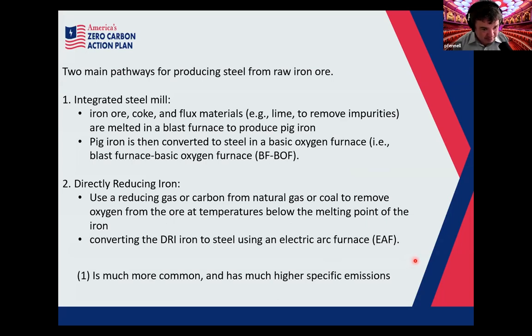There's demonstrations going on, but you have to worry about how much hydrogen you actually need to pull off directly reduced iron. When we did a calculation for a steelworks around the same size as British Steelworks, we found that if you were producing green hydrogen, you'd need the output of a medium-sized nuclear reactor in order to produce enough hydrogen to replace this. So it's a big, big thing to think about.